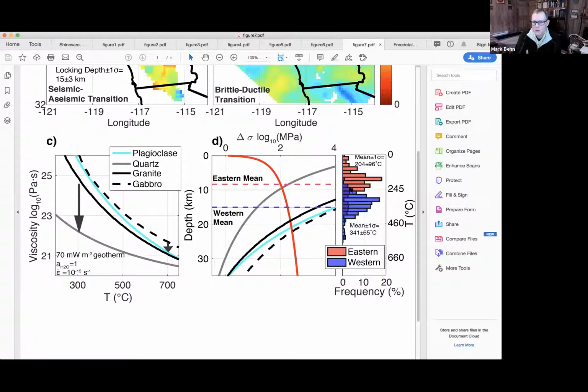But in order to explain this much shallower locking depth to the east, you really have to move towards something that's dominated purely by quartz. So quartz would be the dominant phase. It's the only way to shift that brittle ductile transition up to the shallow. And so that could be pointing towards a transition where you go from an aggregate of a bunch of phases combining to give you one bulk flow law to something that is now just dominated by the weakest phase. And I think maybe it's worth Greg talking a little bit about that,